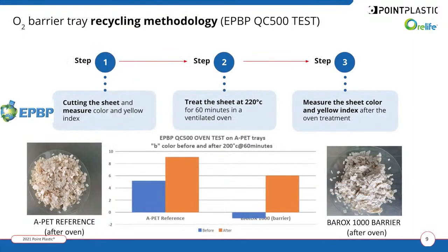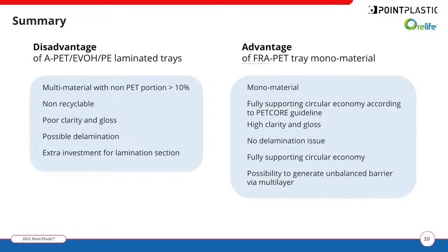This slide shows the data generated during the EPBP QC500 test used to evaluate the recyclability of a PET material. We can see that our barrier solution material shows, after oven test, the same color of reference APET material. The present slide reports the value proposition of our new barrier solution versus the multi-material, multi-layer PET EVOH structure.